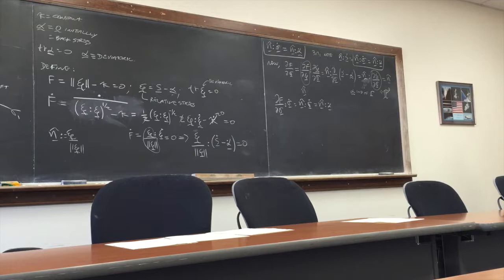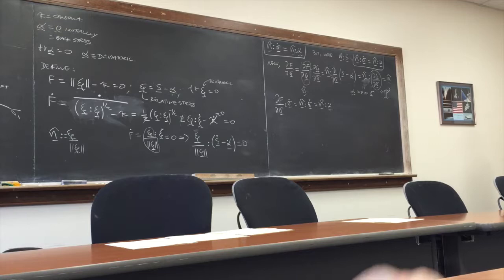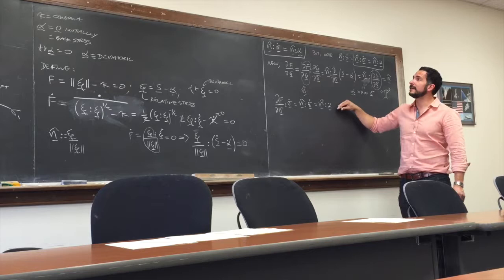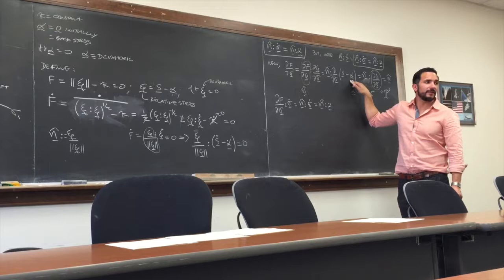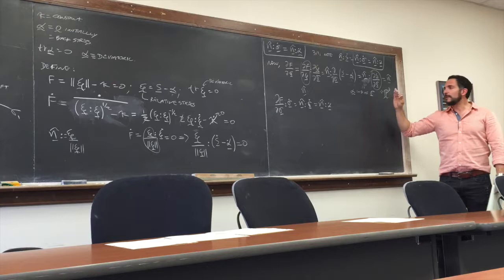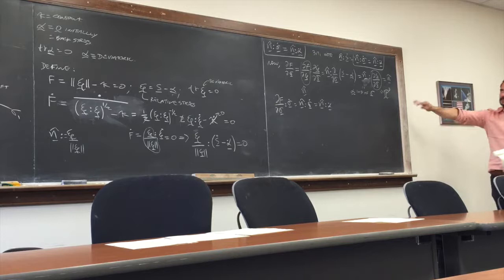There is a closed form derivative, but the same is not true for alpha, not necessarily. So they're independent of each other. And you will see as we give the rule for how alpha evolves. Remember that before we said that one of the principles of plasticity, this is another way to see it, is that the plastic internal variables, here the plastic internal variables alpha, evolve independent of the elastic processes. Sigma is dependent on an elastic process. So whatever happens with sigma never commutes with what happens with alpha. And the opposite is also true. There's this separation between elasticity processes and plasticity processes.